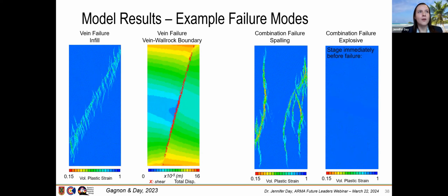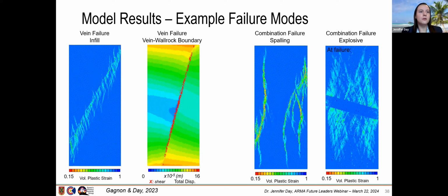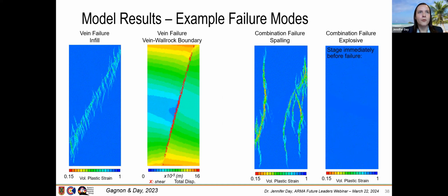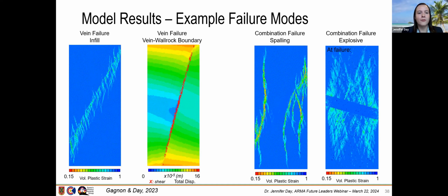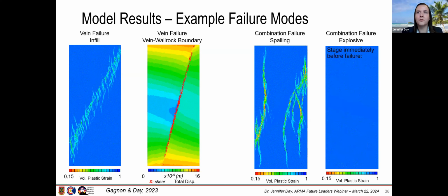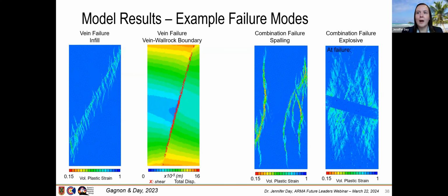On the left, we've got the vein failure through the infill, looking at volumetric plastic strain; the vein failure through the vein wall rock boundary, and you can see the shear failure in the material near that boundary as well. The combination failure of the vein and the matrix, spalling, is on the right, and there's a combination failure of more of an explosive failure where you can see a very rapid change in volumetric plastic strain in the stage immediately before failure versus at failure.